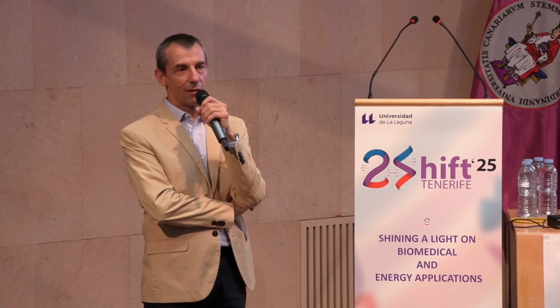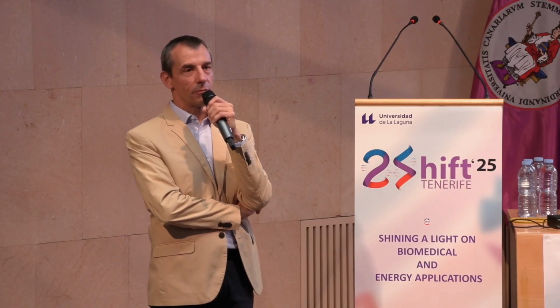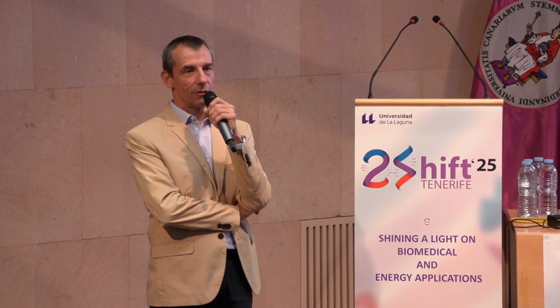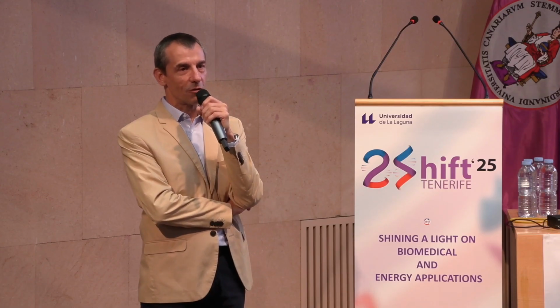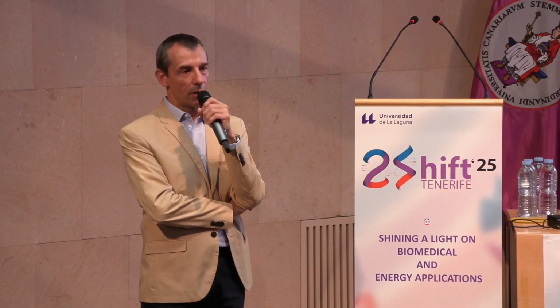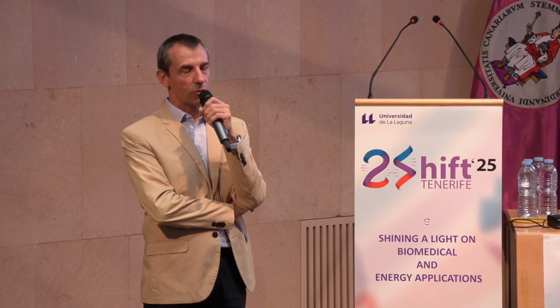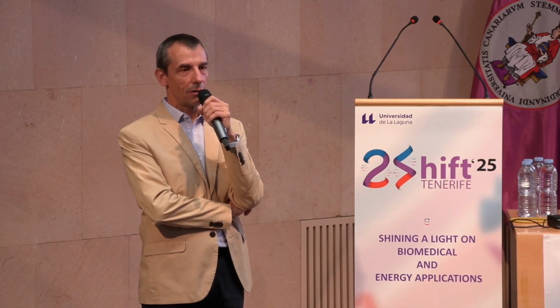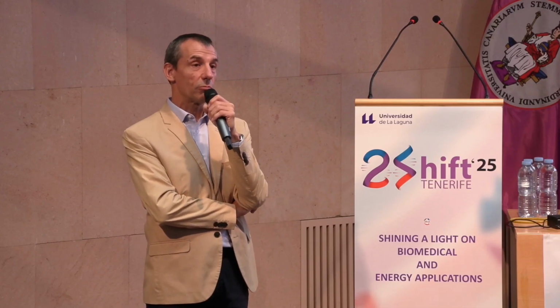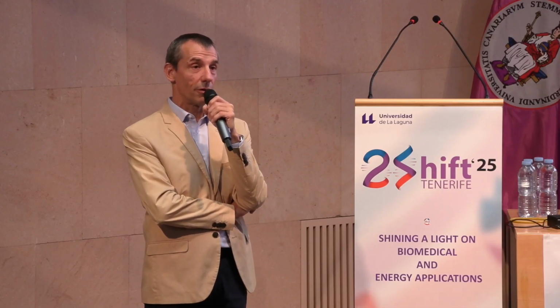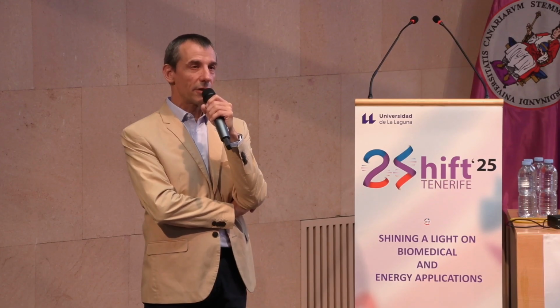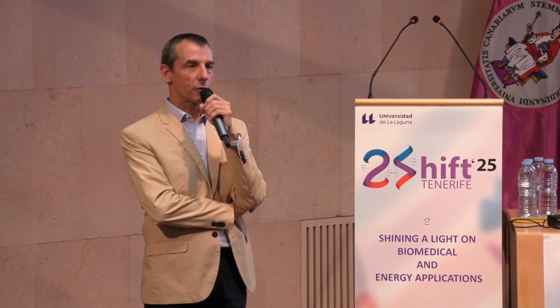I mean, honestly, in quantum technologies, it's a very common technique because a lot of systems work only at milli-K temperatures. And now the question of the temperature of the crystal is indeed a good one. So here I mentioned 50 milli-K. It's a temperature which we call the base temperature, on the holder. The crystal itself is probably at higher temperature. So the spin temperature is potentially 100, maybe even more milli-K.